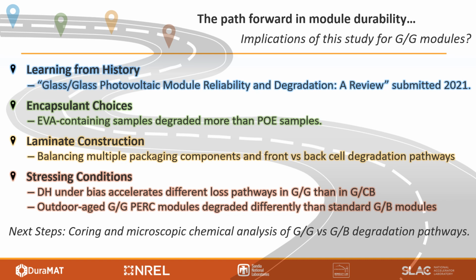Just to recap, we're actively working on building up a roadmap toward greater durability of glass-glass modules. The first step towards this goal was an extensive review article to learn from history and what's been researched so far. We then ran lab tests to understand various factors of the module construction and how the degradation processes change under different stress environments. We found that EVA is generally not a good choice for glass-glass modules, and POE encapsulants can help to avoid many of these degradation pathways.